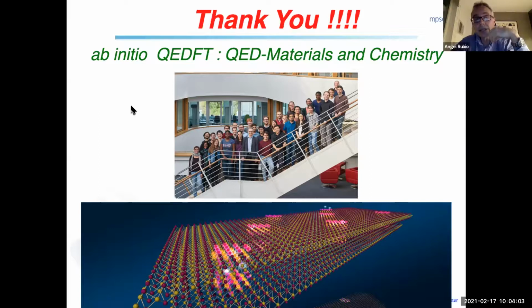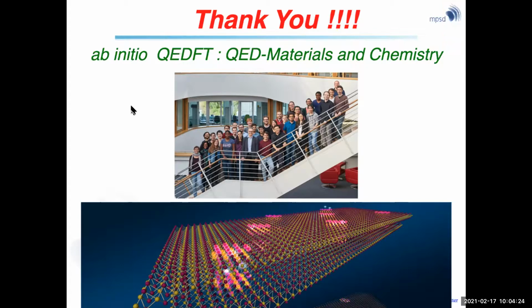And the beauty is, and this is to add, if you did not have the quantum paraelectric, you will not be able to induce the ferroelectric transition. This is something to mention, because this is the non-linearity that you need to have for the cavity to allow you to go from the para to the ferro without putting a strain. No?